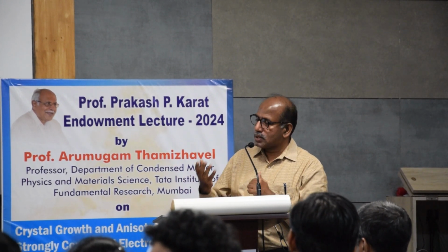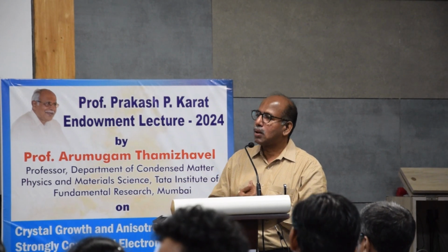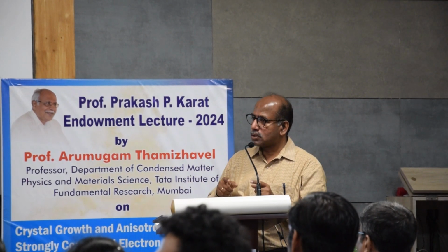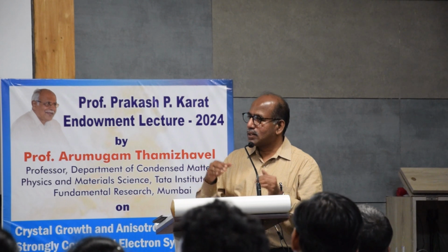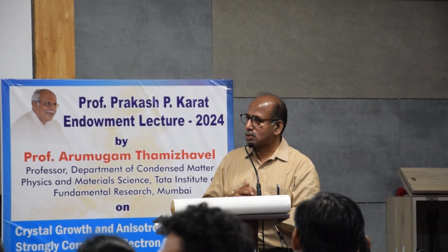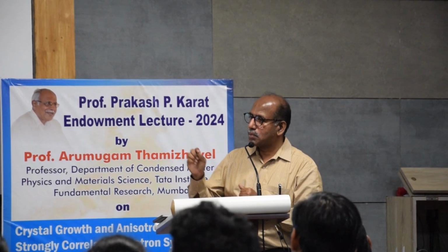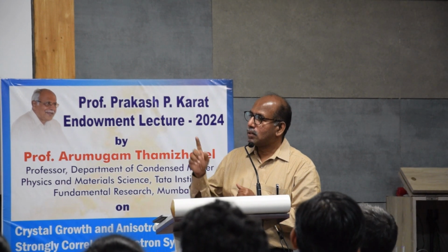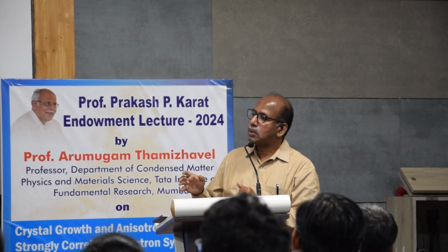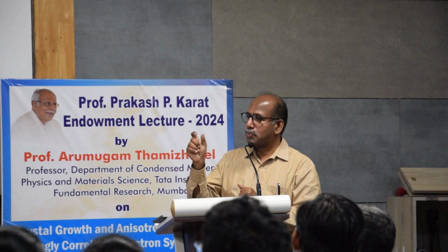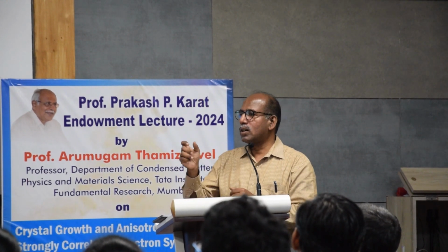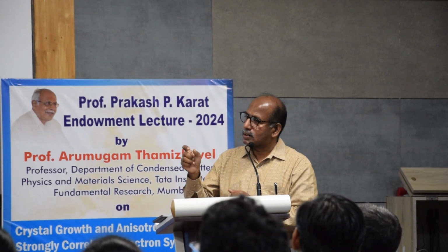One of the famous solvents is the constituent elements, copper oxide or bismuth oxide, copper oxide eutectic composition. These are the things which people have used, and they have grown single crystals, but the single crystals are very tiny. But there is another newer technique which people have used, the optical floating zone. They make a feed rod and a seed rod, and they grow the single crystal.